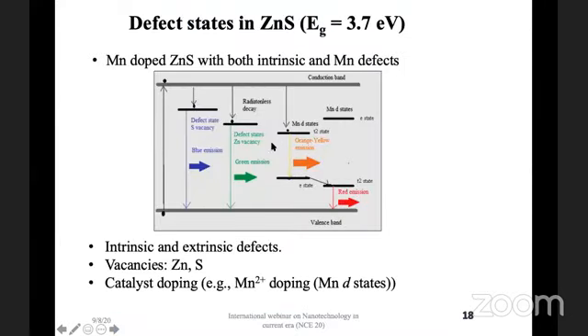Now, why zinc sulfide? It has a band gap of around 3.7 electron volts. It's a wide band gap semiconductor material, highly luminescent, but it has two intrinsic defects, which are zinc vacancies and sulfur vacancies. And when we have these vacancies, these are highly luminescent as well. For the case of sulfur vacancies, we get blue emission, something around 440 nanometers.